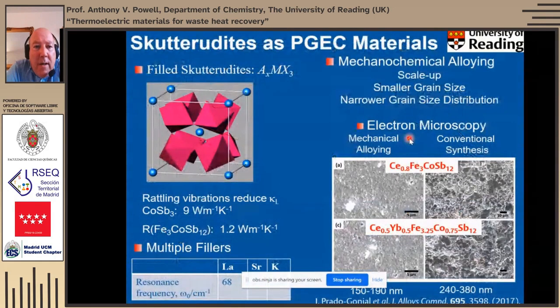Now, I mentioned as an alternative to compositing that there's a class of materials called phonon glass electron crystal materials. So this is some work that our chairman this afternoon actually carried out whilst he was at Reading. This is some filled skutterudite. So here's the skutterudite structure. It's essentially the ReO3 type structure, and in its normal form, something like cobalt antimonide, it has quite a high thermal conductivity. It has no cations in these cavities. It's just that octahedral-based framework.